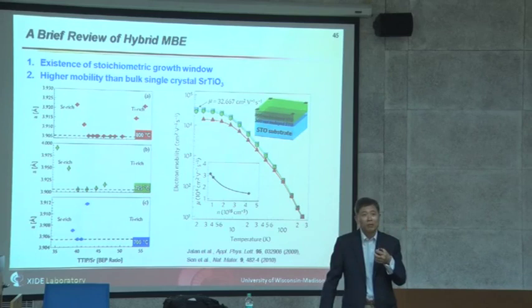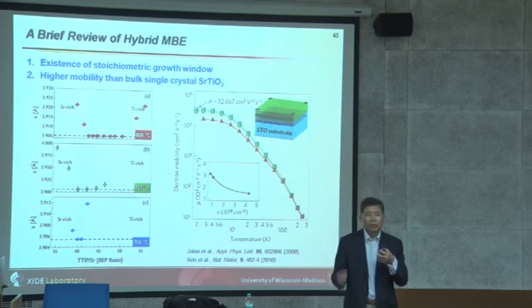Because your RF sputter film is off stoichiometric? Maybe that's the reason. Because you grow the thin films, we happen to see this one. For example, you get strontium titanate, grown very strontium rich, and the strontium rich forms strontium oxide. Strontium oxide in air easily forms strontium carbonate, and strontium carbonate converts, initially, to strontium hydroxide. So that can be easily etched by the water. And maybe your composition is not perfectly stoichiometric, and then maybe PLD is better. So maybe you can try off sputtering, see how it goes.